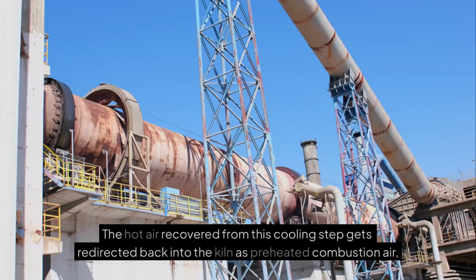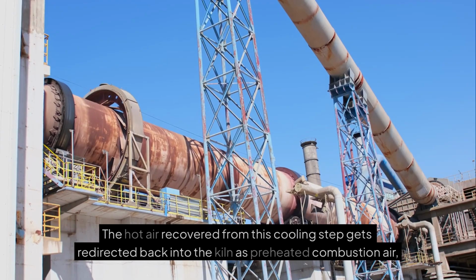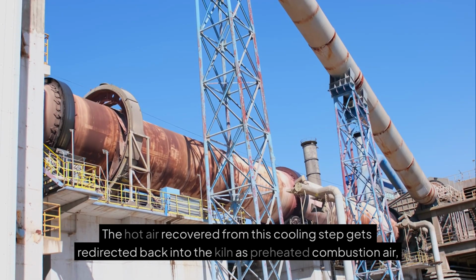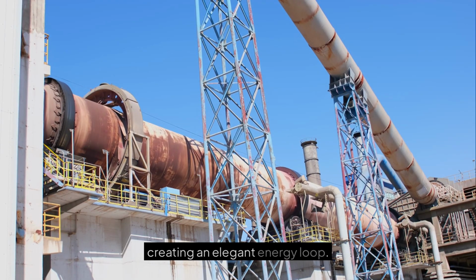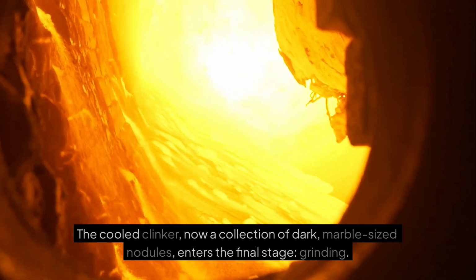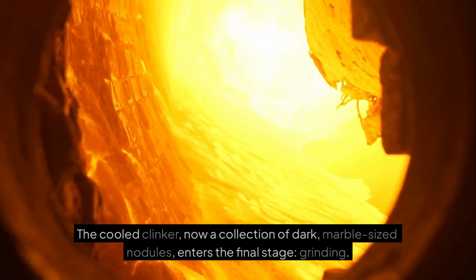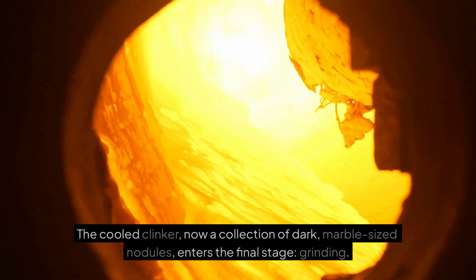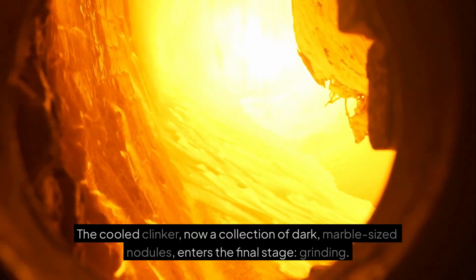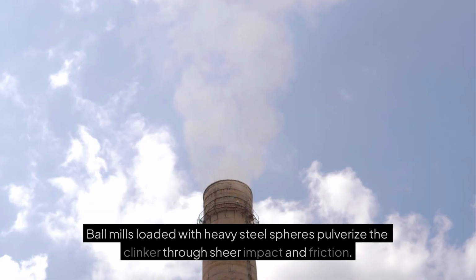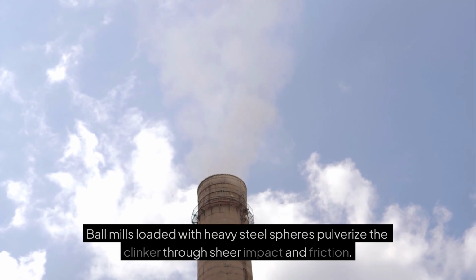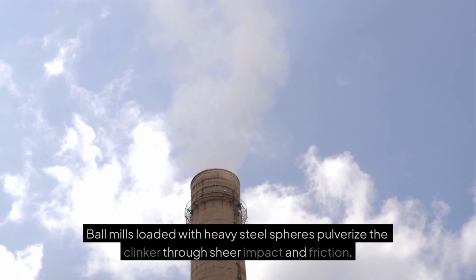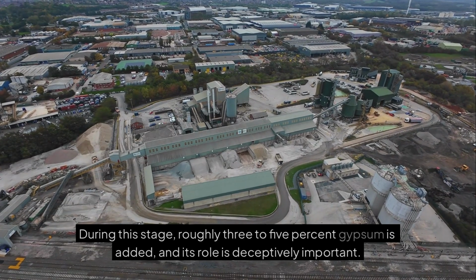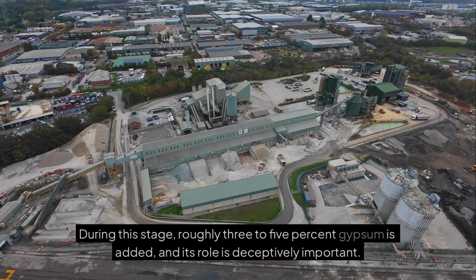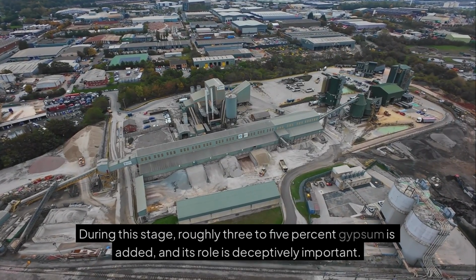The hot air recovered from this cooling step gets redirected back into the kiln as preheated combustion air, creating an elegant energy loop. The cooled clinker, now a collection of dark marble-sized nodules, enters the final stage: grinding. Ball mills loaded with heavy steel spheres pulverize the clinker through sheer impact and friction. During this stage, roughly 3 to 5% gypsum is added, and its role is deceptively important.